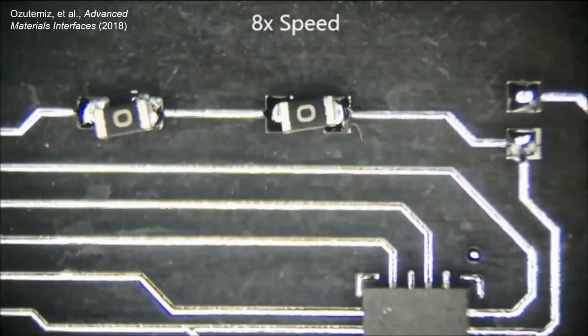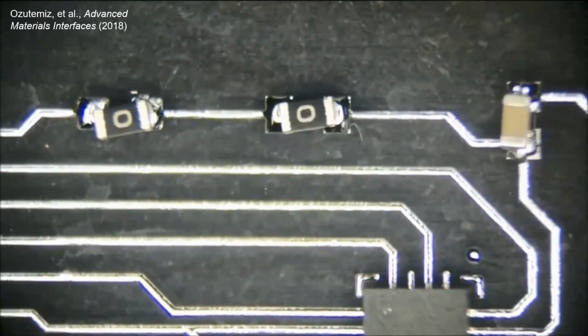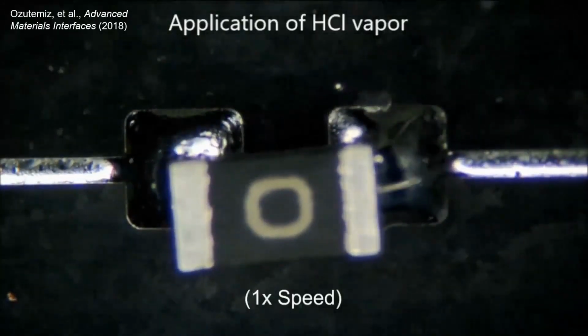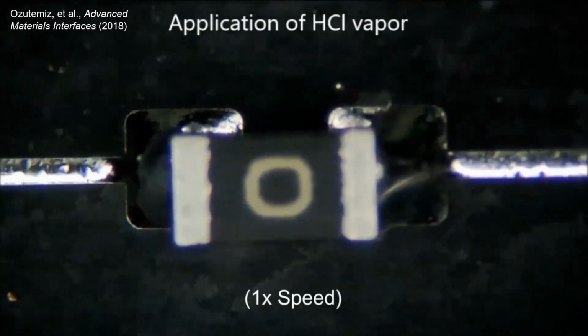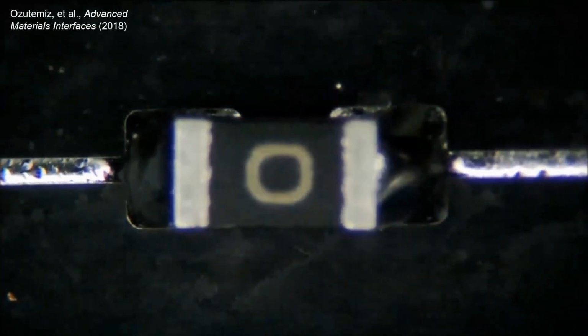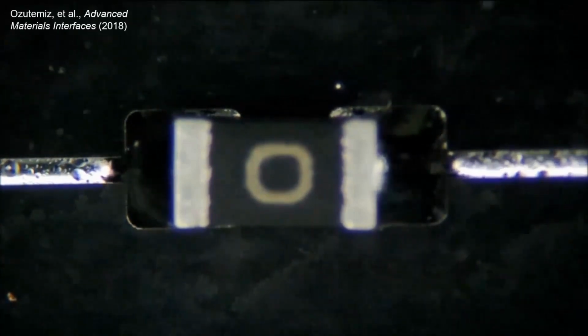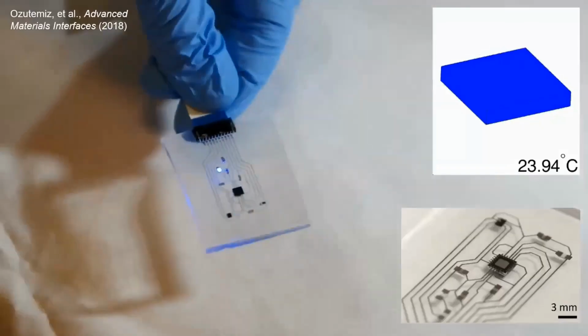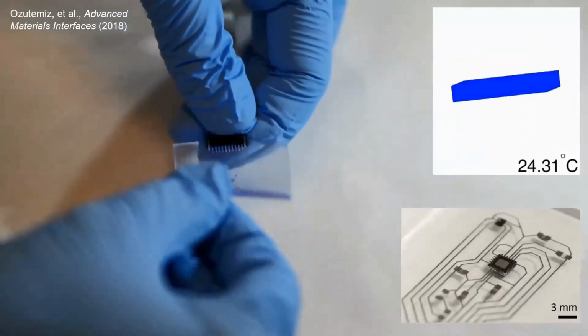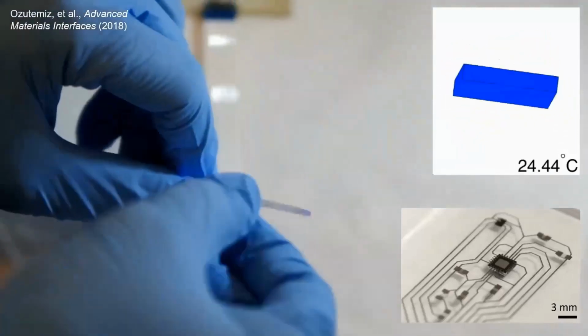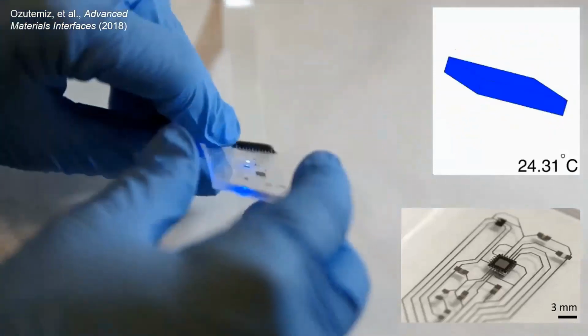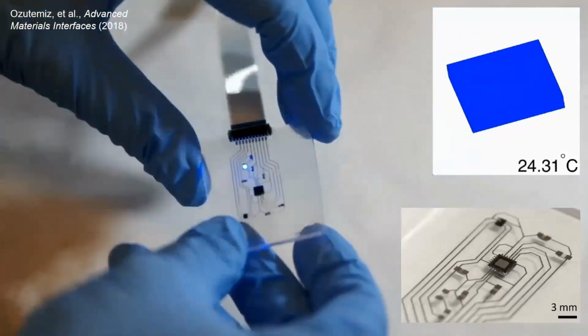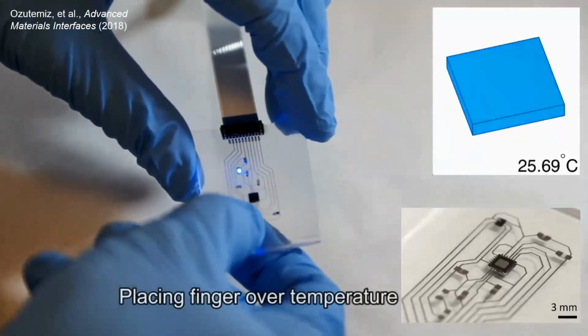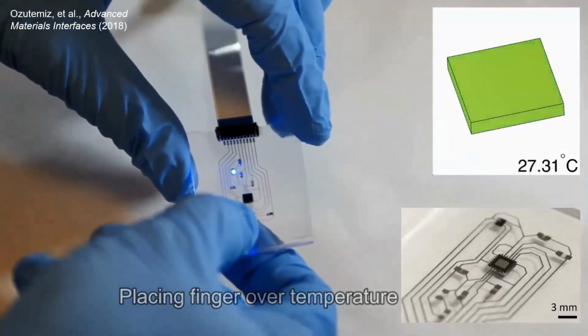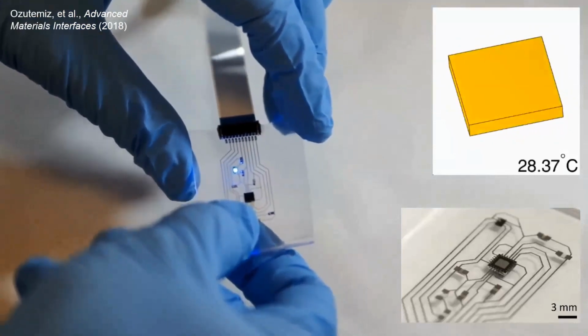And what's funny is that the liquid metal not only functions as soft, stretchable fluidic interconnects, but it also doubles as your solder. You can use a reducing method, just like you would with a flux in more traditional soldering, to mount your electronic chips. Then you can make fully functional digital circuits that can still interface with virtually any packaged IC. In this case, we have quad flat pins, but this really works with gull-wing, ball grid, and pretty much everything else.